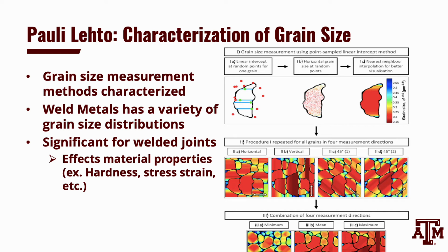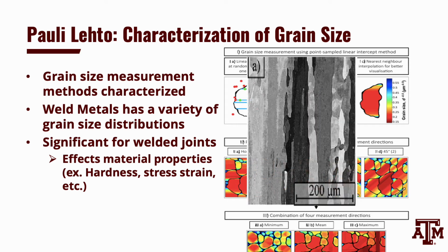Lehto et al. are averaging the grain's width, length, and diagonal of each homogeneous equiaxed grain. If we were to do this measurement on the columnar grains and measure the length and the width and average them out, it is not representative of the grain. Therefore, this method will not work for columnar grains.